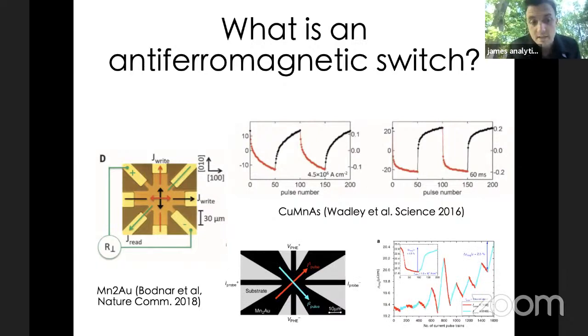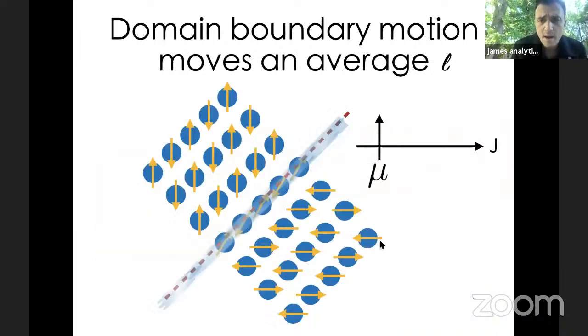The same was seen in the manganese 2 gold, which was actually one of the original proposed materials by the theory, where they see a similar kind of structure, except now it's hundreds or more pulses, and you just keep going into the higher and higher resistance state or lower and lower resistance state. So there's a lot of work, and I would say pretty clearly demonstrated that something interesting like this is happening.